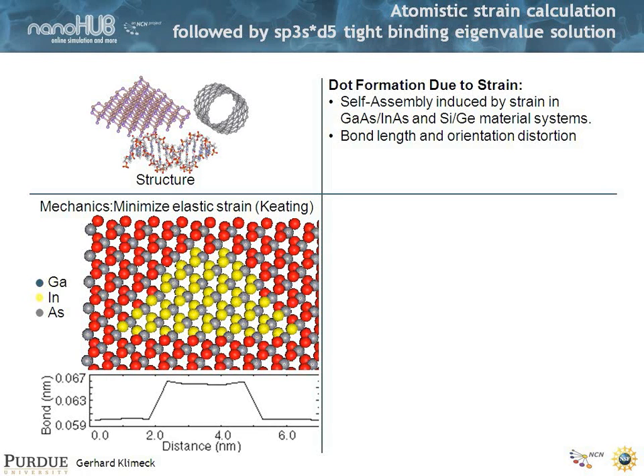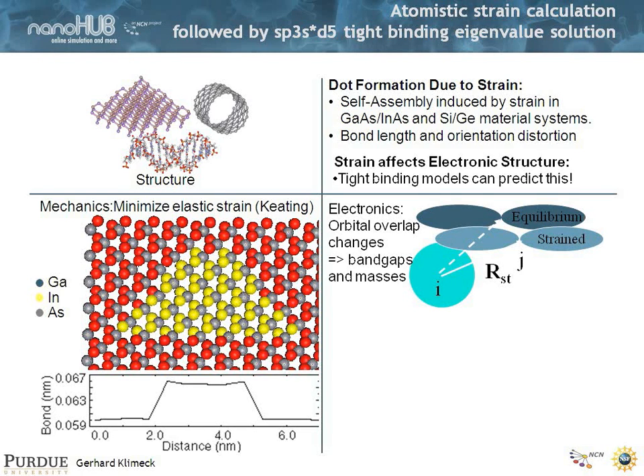What I sketched here is a sliver of a quantum dot. If you take a slice and look at the bond length through the structure along the lateral distance, you see a small bond length change from roughly 0.059 to 0.064 or so — a relatively small change. But if you think about orbitals interacting from one atom to the next — say an s orbital interacting with a p orbital — and you change the angle and distance slightly, on a quantum mechanical level you change the overlap of those matrix elements and wave functions quite significantly.